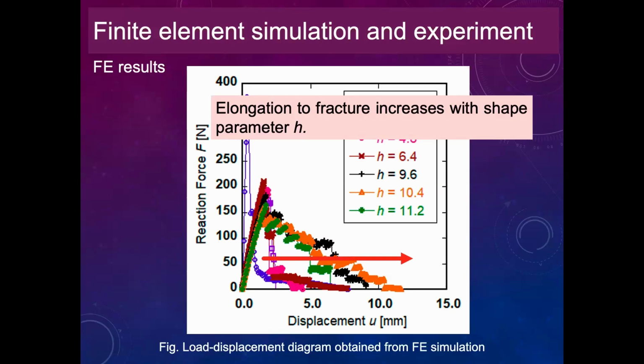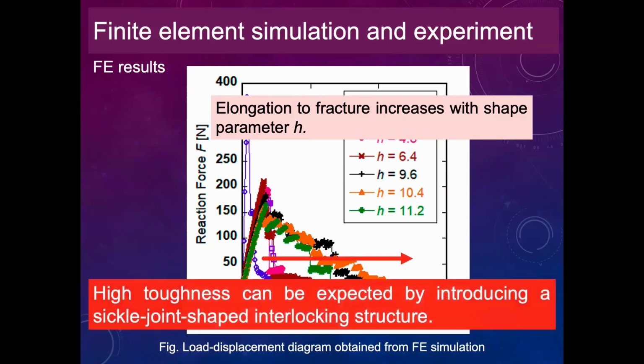It can also be characterized from this result that after reaching the maximum load, the load decreases stepwise as shown here, regardless of the shape parameter H. From this FEM result, it was found that high toughness can be expected by introducing the Sickle joint shaped interlocking structure in the CT specimen.